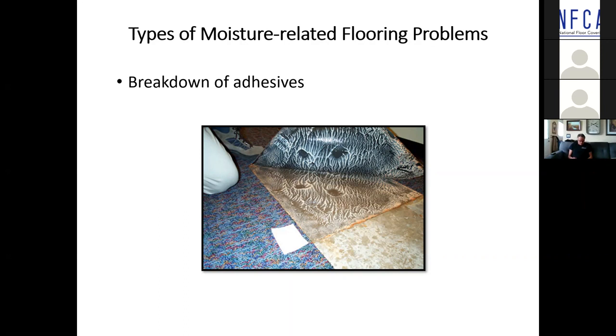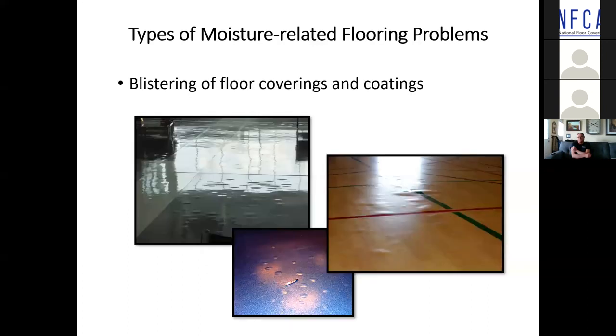That water that rises to the surface, and those of you who've placed concrete or seen it placed, you see it, bleed water, but it's not pure water. It contains any chemical, any admixture that's in the concrete, or alkalis, soluble alkalis. And that's why everyone who's ever seen a test done, you always see higher levels of sodium and potassium ions in the top 3 millimeters of the concrete than you do deeper in the core. Okay. And it's those alkalis that, when they go into solution, raise the pH of the concrete up to a level that can begin to attack and break down the adhesive, and so on and so forth.